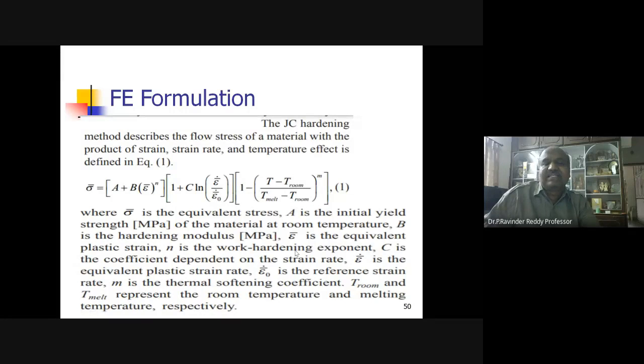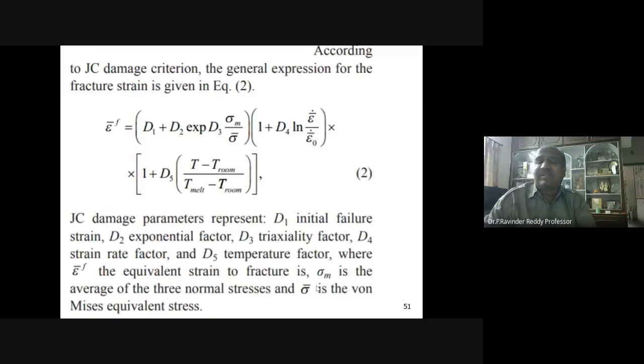So if you see, sigma bar is the equivalent stress, A is the initial yield strength of the material, which we know at room temperature. B is the hardening modulus. Epsilon is the equivalent plastic strain which we are going to measure. N is the work hardening exponent. C is the coefficient dependent on the strain rate, and epsilon dot is the equivalent plastic strain rate. And again, we can have a reference strain rate. M is the thermal softening coefficient. And the room temperature and so on we specify for the same.